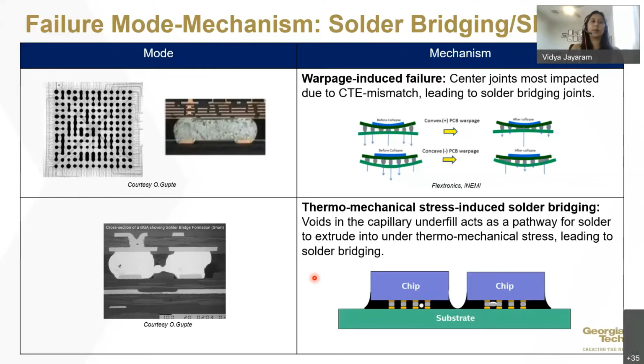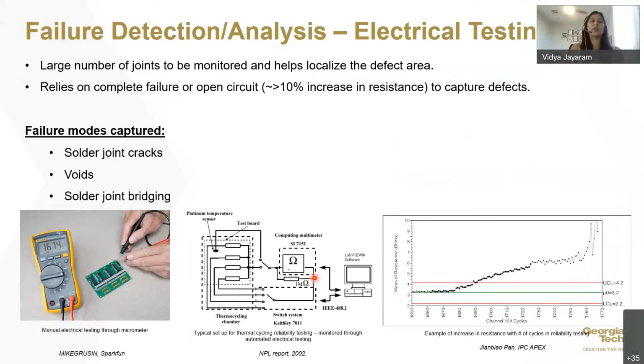We have looked at some typical examples of failure modes seen in chip and board level interconnections. So let's look at how we can detect these failure modes so that we are able to study them better, detect them, and work towards prediction and improvement. Electrical testing is a quick and relatively common testing method to check for solder joint bridging or open circuits. The good part is a large number of joints can be monitored, and you can help localize the defect area. However, it relies on complete failure or open circuit to be detected, which is around a 10 to 20% increase in resistance to be able to capture these defects.